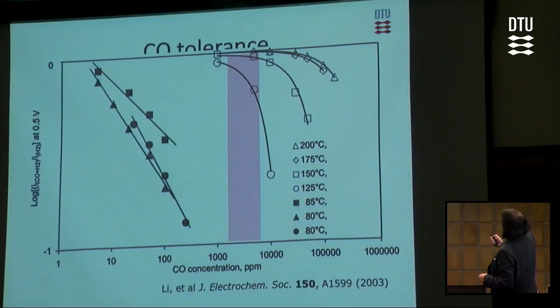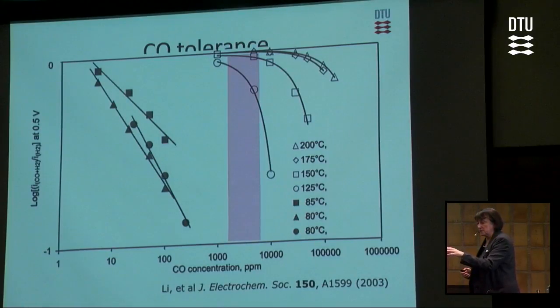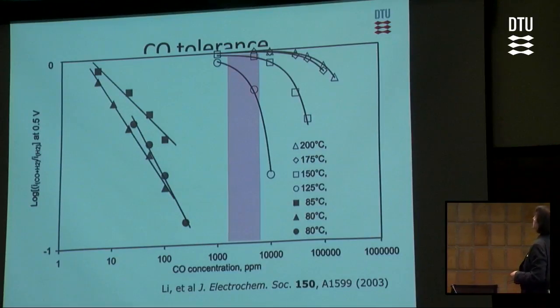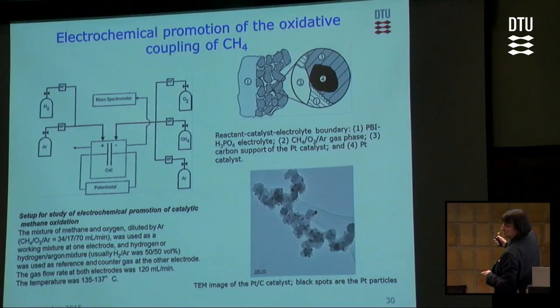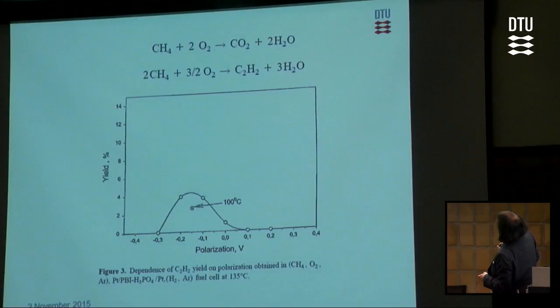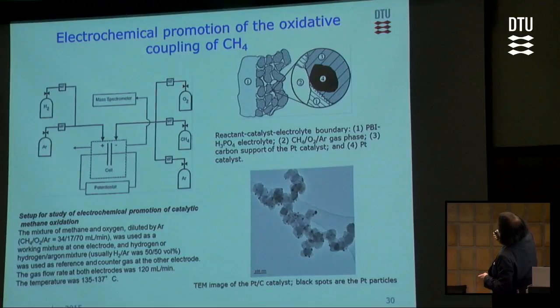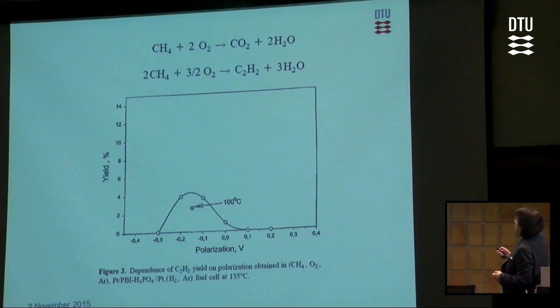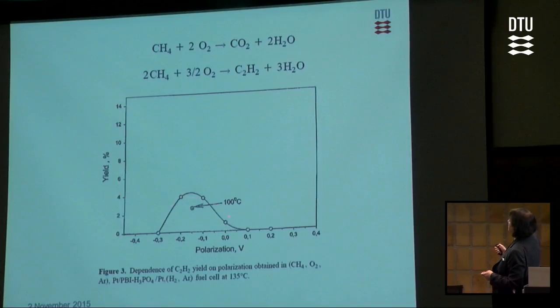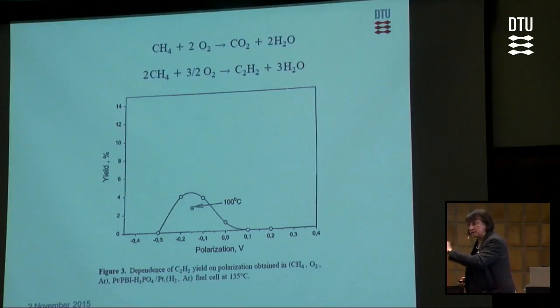So it means that tolerance of the catalyst to CO will be hundreds of times higher. So if the temperature of a PEM fuel cell is higher than 100, you have better tolerance and you can study more reactions. The first reaction under study, we also use a mass spectrometer here online, was the oxidative coupling of methane, a very unusual way of doing this kind of reaction at these temperatures. What we got here is a yield, maybe not very high, around 5, but it's at 135 degrees, of acetylene. We specifically used a chromatograph to confirm that this is acetylene. And actually, with several runs, it could be quite good.